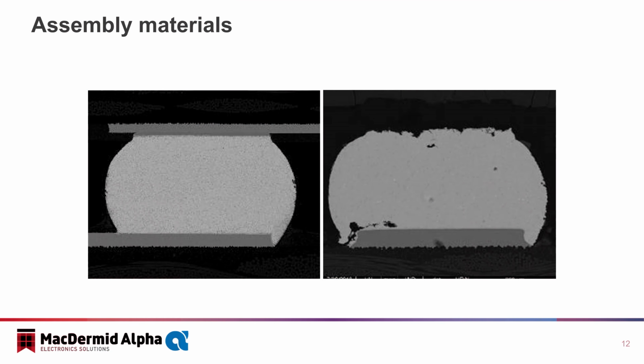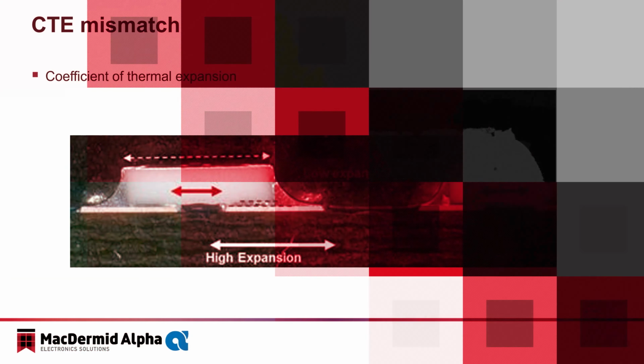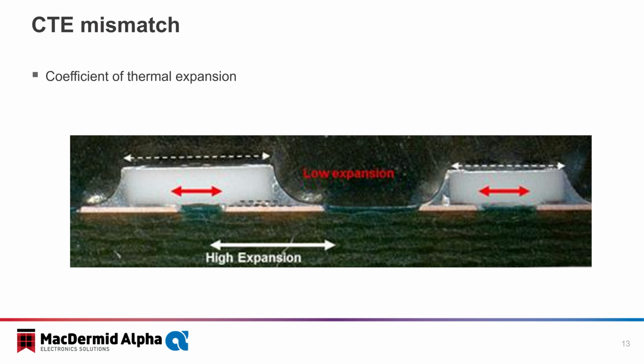The predominant area of weakness is the solder joint interface. Thermomechanical forces put stress on the solder joint, and eventually that stress releases through a crack, and this crack can become an electrical failure. The best way to eliminate this failure would be to enhance the solder alloy.